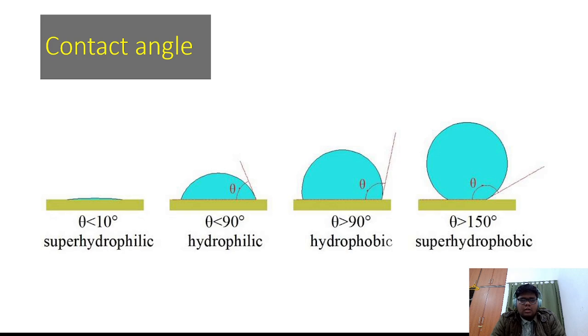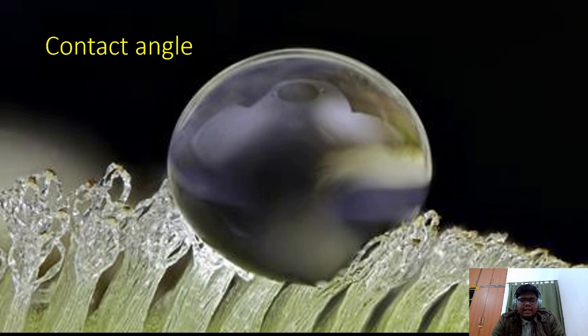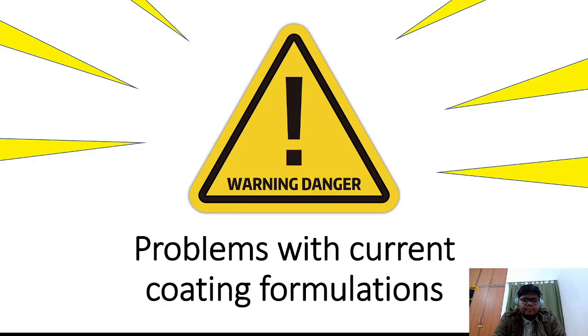further. A surface is defined as hydrophilic or hydrophobic based on the contact angle between solid and liquid. For superhydrophilic, this angle is less than 10 degrees. For hydrophilic, this angle is less than 90 degrees. For hydrophobic, this angle is greater than 90 degrees. And for superhydrophobic, this angle is greater than 150 degrees. In nature or in synthetic process, whenever we want to make a surface super hydrophobic, we make it by making hierarchical nanostructures, as you can see in this picture.